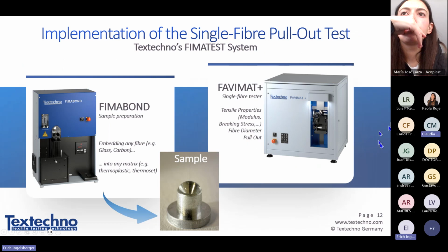This is the setup which we recommend. Favimat, I have already introduced briefly. It is a single fiber tensile tester. It measures the tensile properties, fiber diameter, and it can do pull-out testing. Maybe here you can see a little difference: before we only had two clamps, upper and lower, but now we have an upper holder and a lower clamp to pull out the fiber. I will show you in detail.